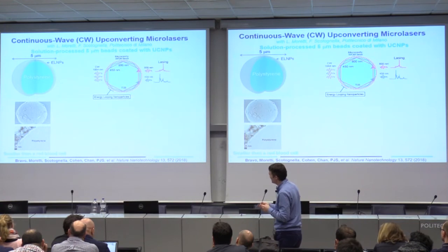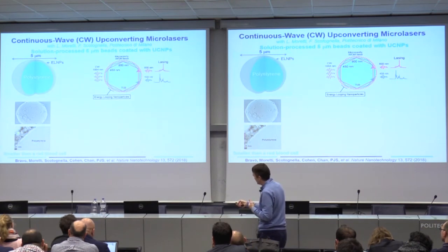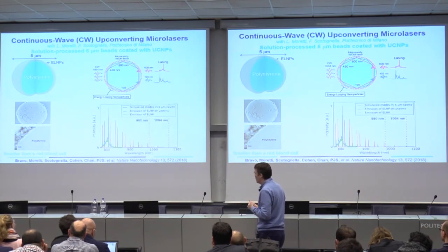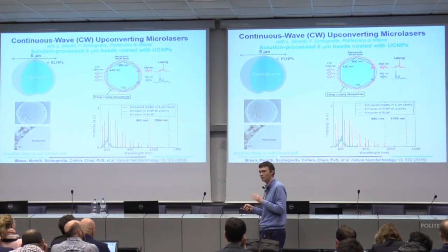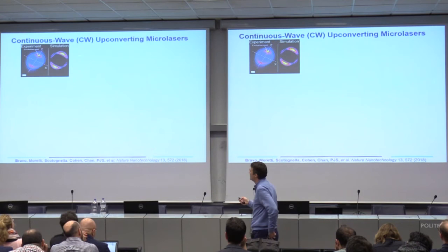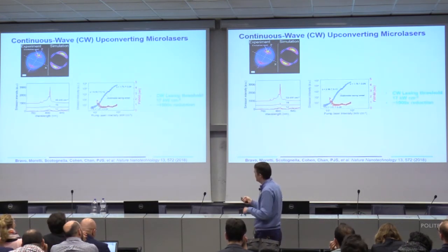This is what they look like. These are the polystyrene beads. You can see they're not particularly pretty, but they work well. So, polystyrene coated with upconverting nanoparticles. And we did this, and what you saw immediately was these neat, sharp lines. I'm like, oh, this is promising. And it turns out that, in fact, they do lase. You start turning up your pump power, and you do see that they lase.